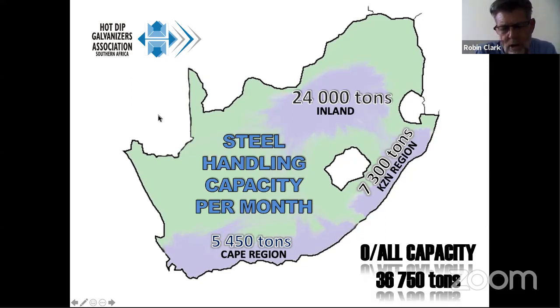So we have approximate capability inland of doing about 24,000 tons per month of steel. The KZN region is in the order of about 7,300 tons per month of steel, and the Cape region, stretching from East London down to Cape Town itself, approximately 5,450 tons of steel. The big issue there is there are two elements that we need to understand. That is that kettle size and heating capacity are the two prime drivers for the ability of the galvanizer to process tons of steel per hour.